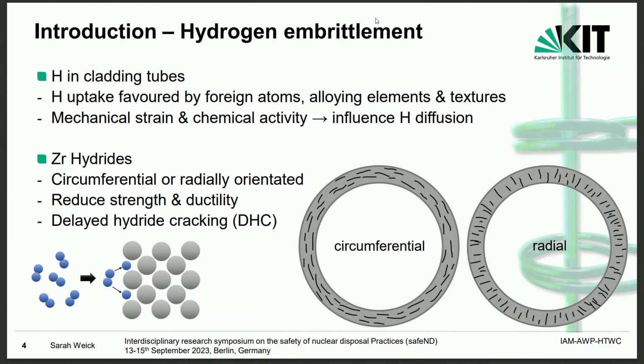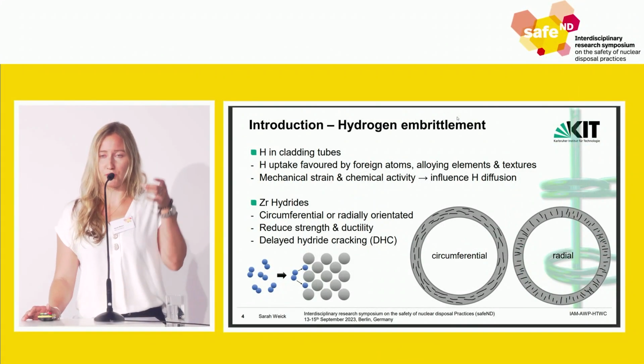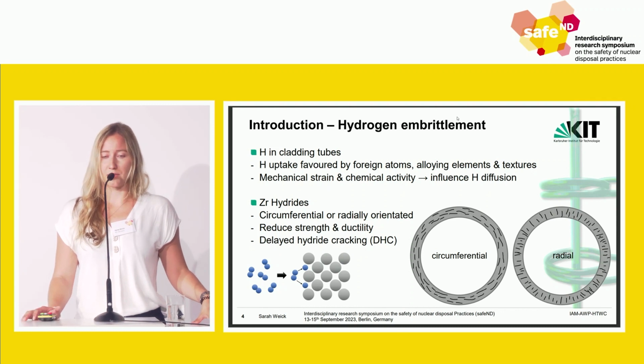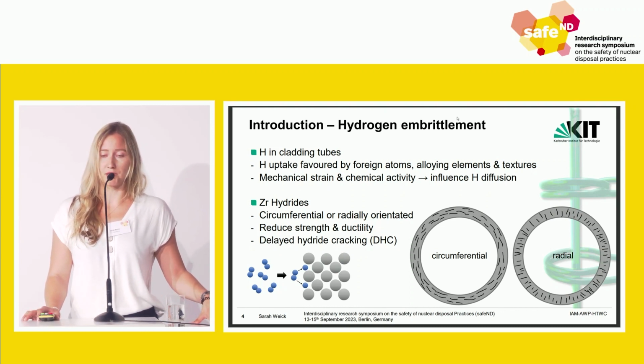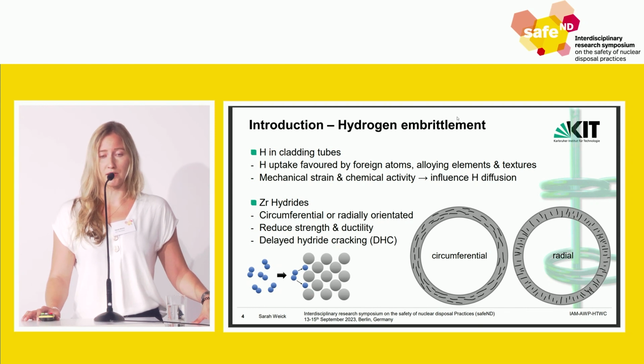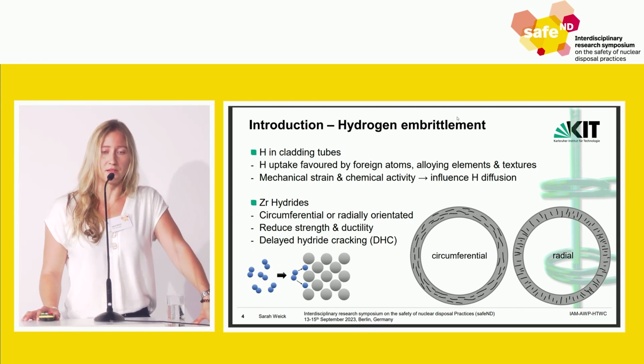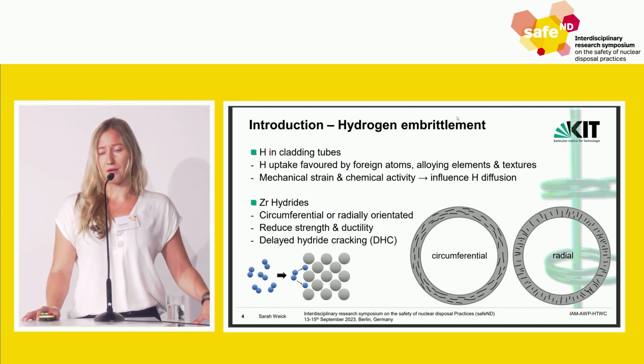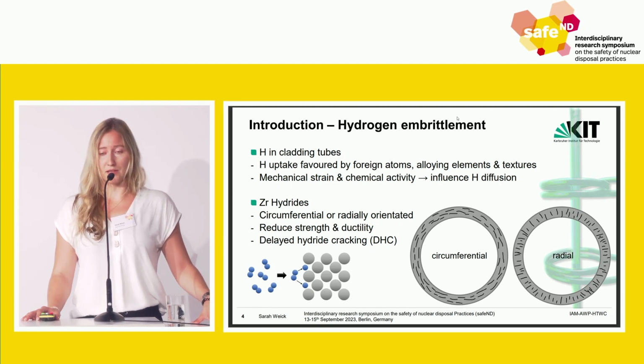What happens when the hydrogen is not in a solid solution anymore is that it precipitates in different forms. In the cladding tube itself, which has a tube form, it can precipitate as circumferentially oriented hydrides or radially oriented hydrides. The difference is that radially oriented hydrides have a more destructive influence on cladding tube stability, potentially leading to delayed hydride cracking, for example.